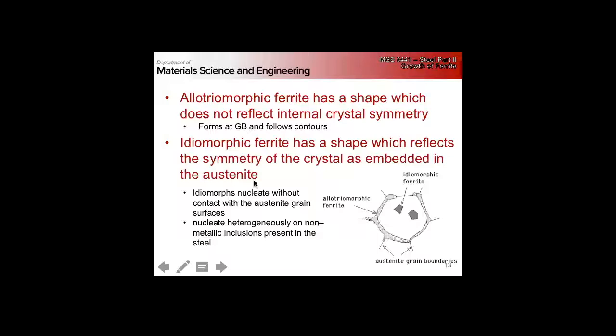And then idiomorphs, which nucleate heterogeneously from an inclusion in the crystal, but grow as basically a single crystal of ferrite, having faceted shapes that reflect the symmetry of the ferrite crystal. These nucleate without any contact with the austenite grain boundaries.